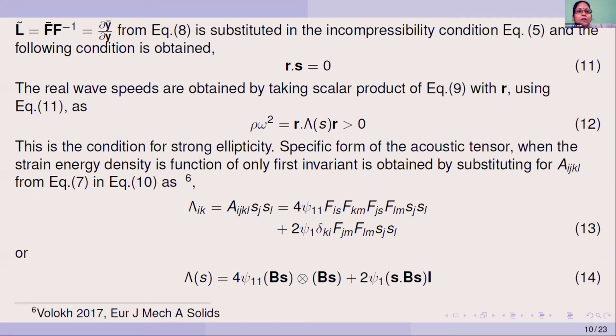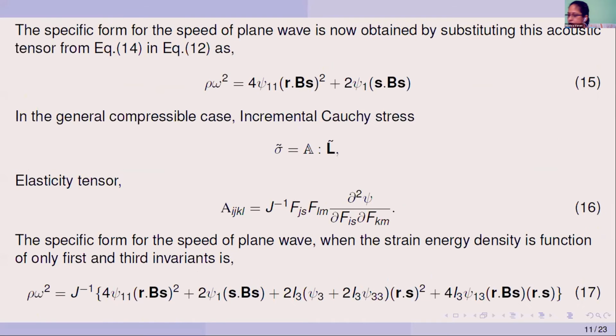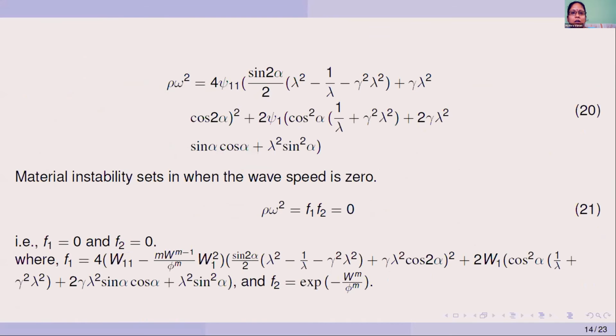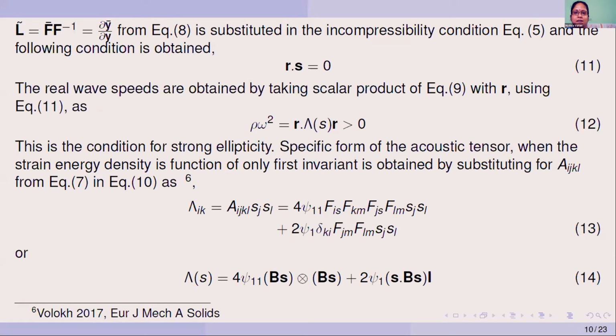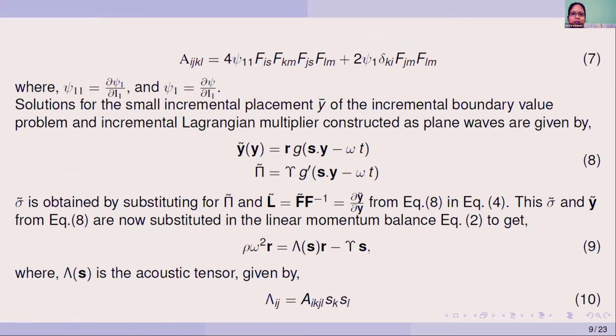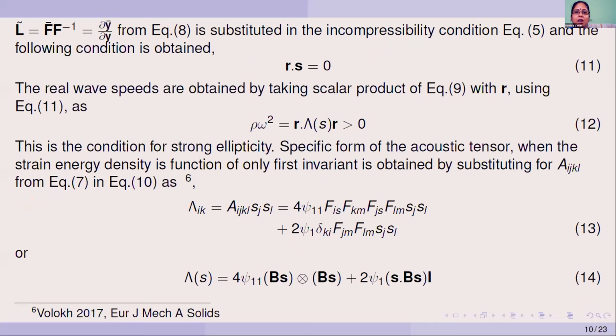So then we plug in this incremental velocity gradient L tilde back into the incompressibility condition equation 5, and we obtain this orthogonal relation between the unit vectors R and S. So now we go back to this equation 9 and take scalar product with this unit vector in the wave polarization direction R, and we use this incompressibility condition, and we obtain this equation 12 for the wave speed, and this wave speed is always positive for the condition of strong ellipticity to be satisfied.